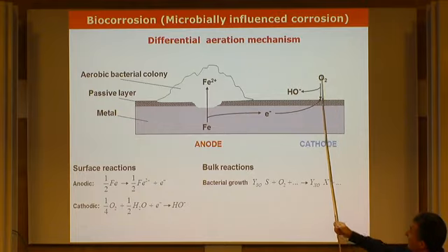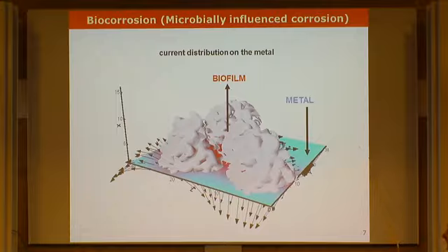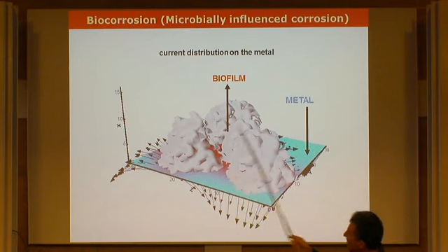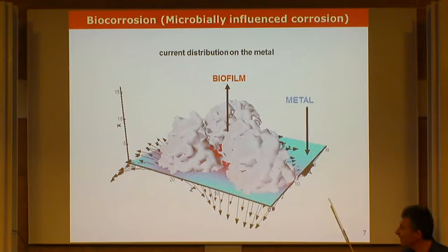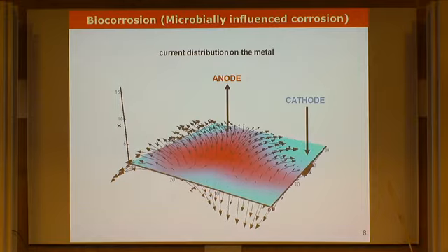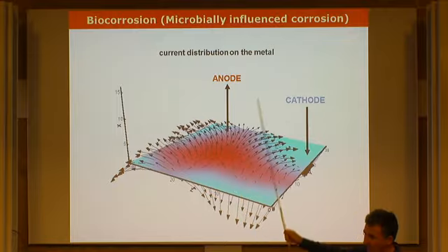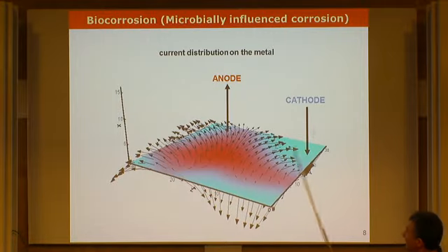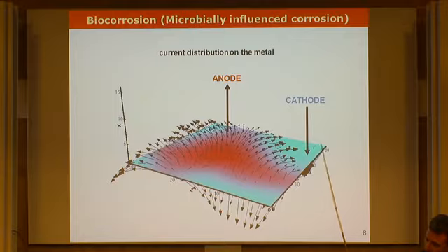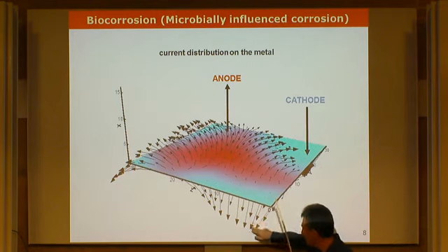Now, if you try to put all these reactions in a closed system and also simulate the transport of ions and the transport of electrons through the metal, what you get typically with these simulations is the current distribution on the metal surface. So imagine this white patch here. This is the biofilm, a few colonies of bacteria, and this is the metal surface. So if we remove the biofilm, we can see that under this colony you have anodic currents. Anodic currents, these with red and arrows pointing up, means that you release ferrous ion in the solution under the colony. And you should have also enough cathodic space so that oxygen is reduced.